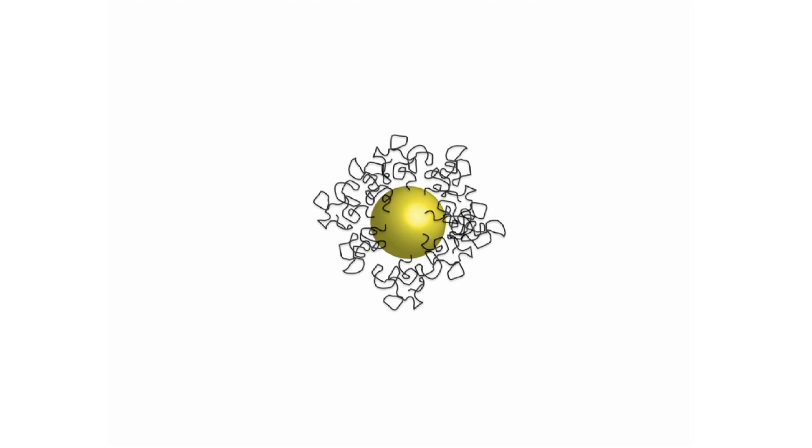Well, we've been working to understand how to improve the delivery of hydrophobic photodynamic therapy drugs in vivo using nanoparticles. Laser spectroscopy provides critical insights into how molecules interact with nanoparticles in solution. In our system, we have a gold nanoparticle coated with an amphiphilic ligand called polyethylene glycol.